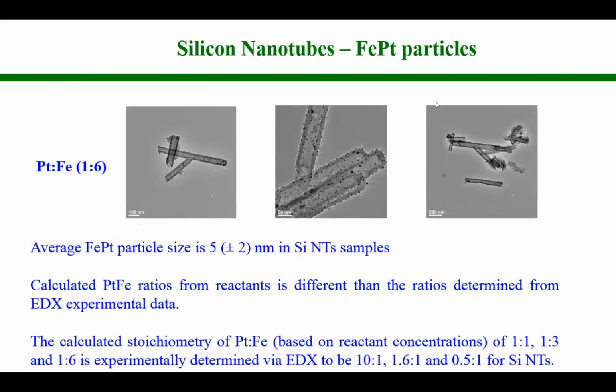So this formation has been done for various ratios of platinum to iron. It has been done for 1:1, 1:3, and 1:6. And here you see an example of a ratio of 1:6. You see the iron platinum particles inside the tubes, and the average size of the particles is 5 nanometers.